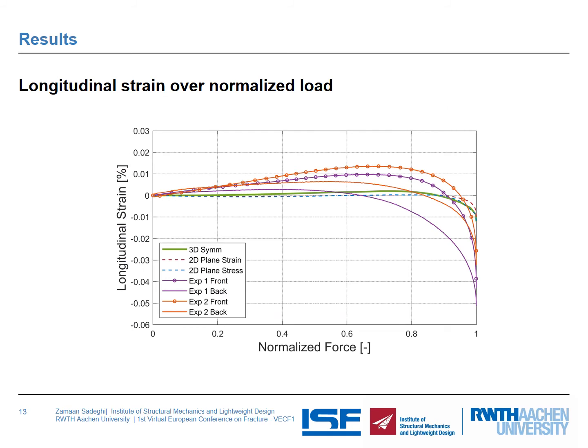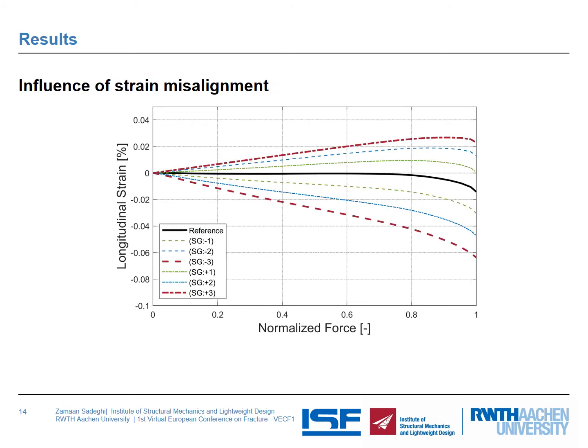So in this slide, longitudinal strain over normalized load is illustrated. As you can see, more or less the same trend can be observed as in the previous slide. There is almost no general good agreement between FE predictions and experimental results. But what could be the possible answers for such a discrepancy between the experimental and FE analysis, in spite of the fact that the FE analysis was able to predict the failure load at a very good and accurate level? One of the possible reasons that could lead to such a discrepancy is the strain gauge misalignment. But how big is the influence of strain misalignment on the strain which is recorded by strain gauges?